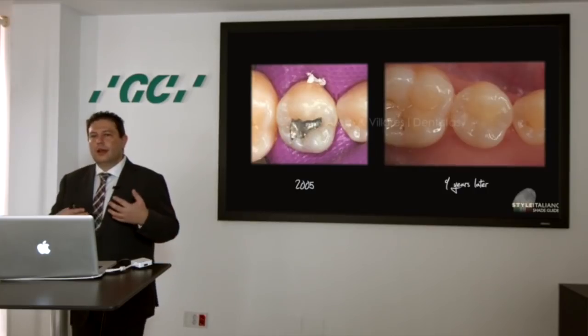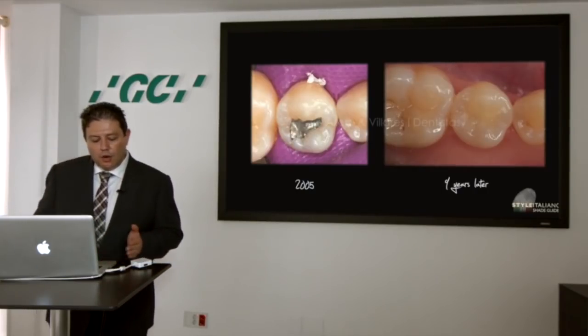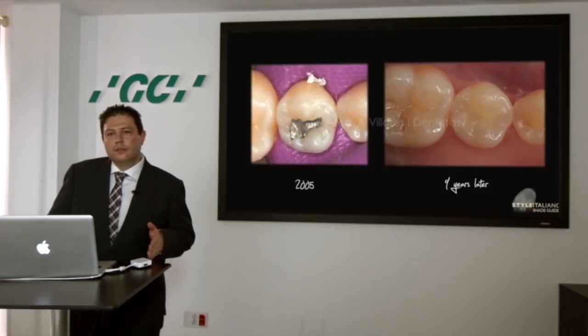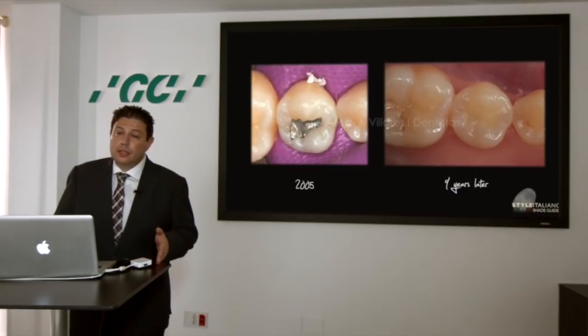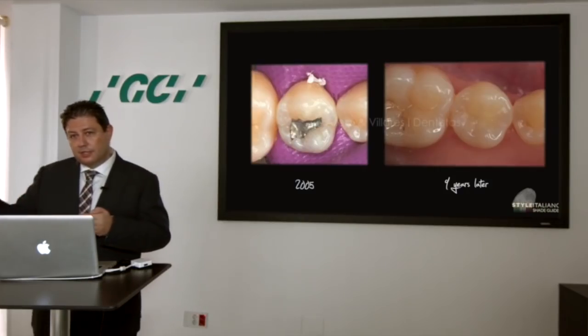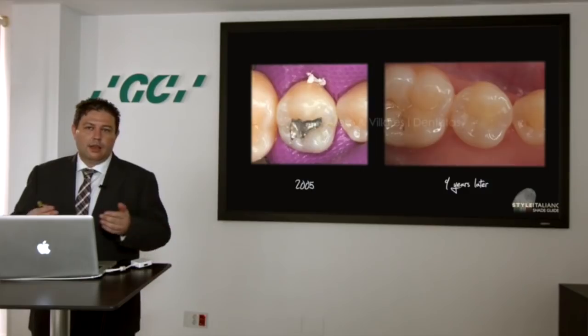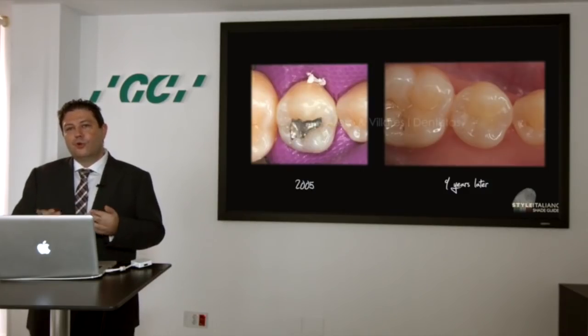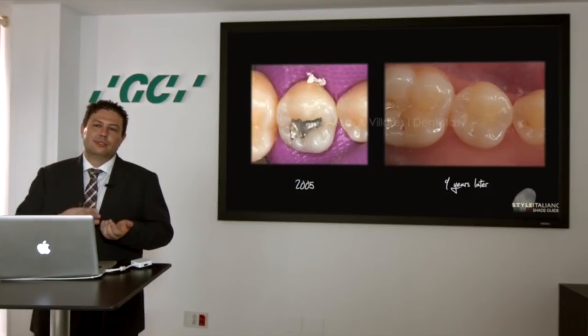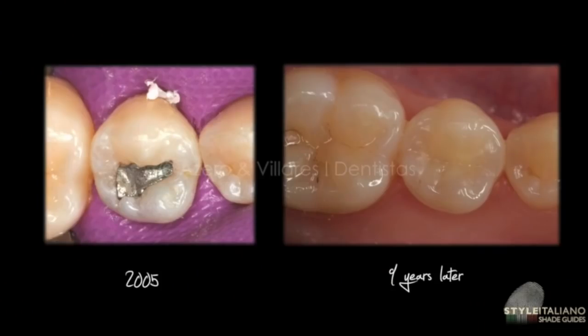But what we can answer our patients is, okay, we know that the literature says that after 5 years we can have some degradation of the interface between the material that we're using and your teeth. And what we're doing now is putting all our knowledge to improve this, and we are using the latest techniques to make it last, for example, more than 5 or 7 years in your mouth. And now what we realize is that if we use the adhesive in a proper way, we have very good success. The problem is normally dentists don't use the products in the proper way.